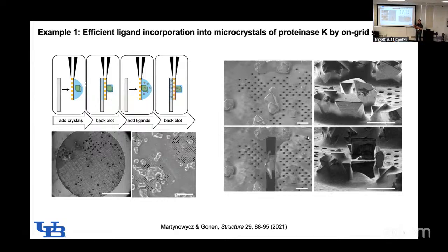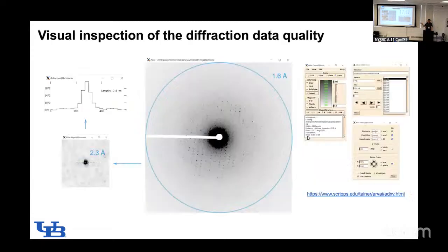And the great thing is that chamber is humidity and temperature controlled. So we usually just let it sit there at 4 degrees Celsius with 90+% humidity. We can let it sit for minutes, hours, usually just a couple of minutes, and then blot it again. And so we did that on proteinase K crystals. I did this before COVID, and then I wrote this up during COVID. Milled them, and from a single crystal, we were able to get some good ligand density.